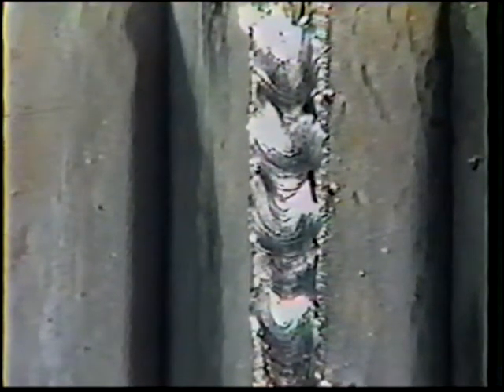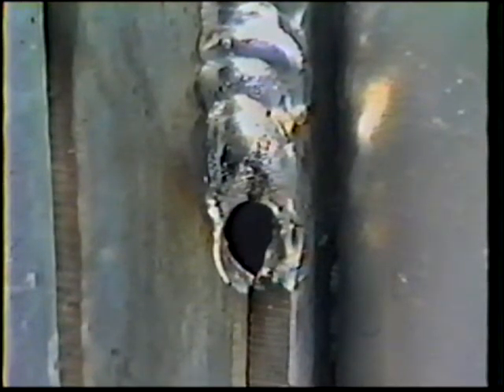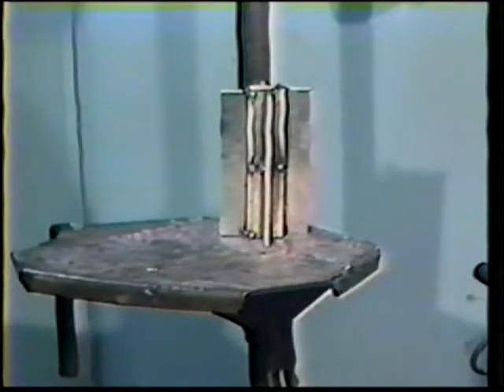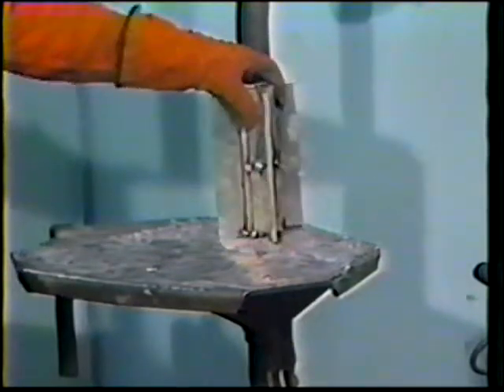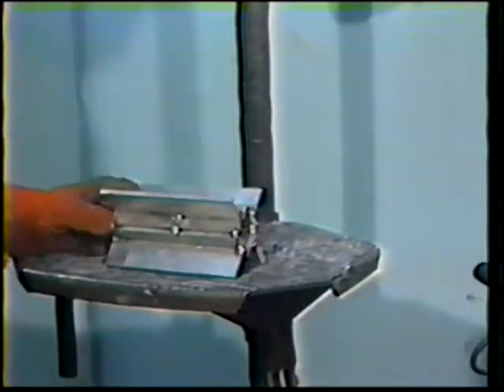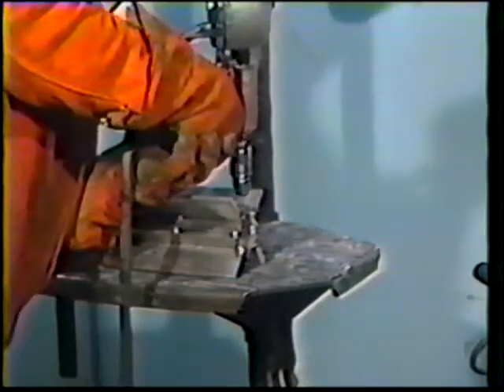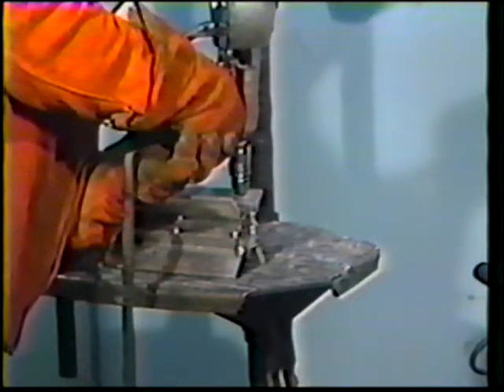Proper gun angles and travel speed are essential for correct welds. The 90-degree work angle prevents undercutting along the edges of the joint. Improper travel angles or a slow travel speed will create excessive heat buildup and may result in overpenetration or melting through the joint. Set the first workpiece aside and weld another corner joint on another piece. Continue to alternate pieces until all the corner joints on all the workpieces are welded.